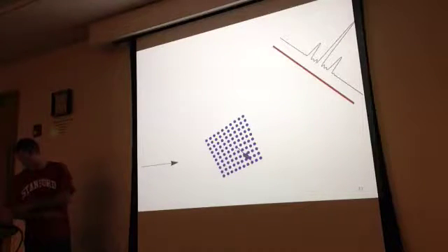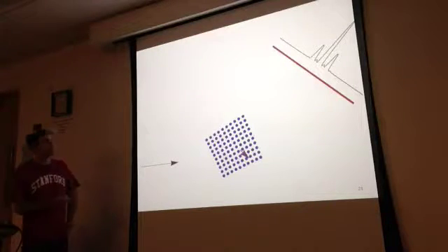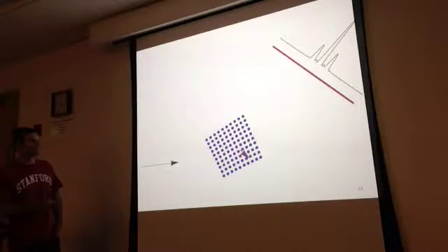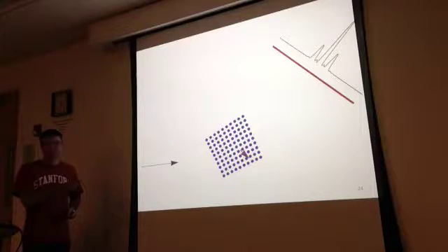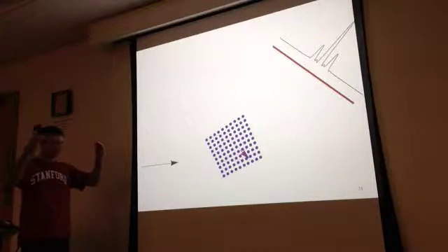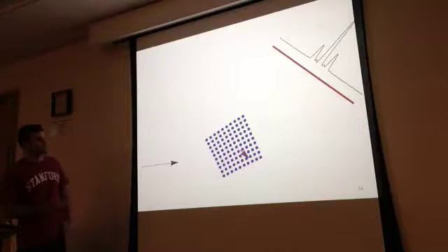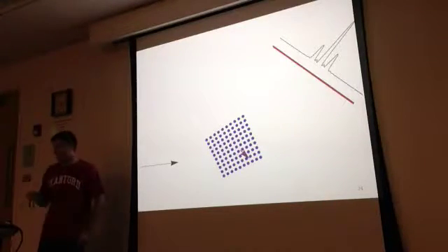So these side peaks will get closer to the Bragg peak, and if I make it shorter yet, they'll get even closer. So what we can see is that this line detector is really imaging the reciprocal space of the crystal for us. The Bragg peak is marking the position of zero wave vector. What we're really doing is imaging a one-dimensional slice of the two-dimensional reciprocal space of this crystal. And what you're going to see later in the talk, when we use a three-dimensional crystal and a two-dimensional detector, is we'll be looking at a two-dimensional slice of the three-dimensional reciprocal space of that crystal. So basically, different points on the detector correspond to different phonon wave vectors.